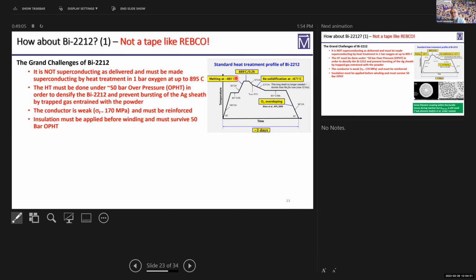And then we've lost oxygen up here, so we've got to let the oxygen keep going all the way down here. But the other issue is that because powder-in-tube has kind of 30% of void space, typically air, i.e. nitrogen and oxygen, oxygen can freely escape through silver, but nitrogen can't. So unless you provide an overpressure of, in this case, argon, so we have 49 bars of argon, 1 bar of oxygen, then it just bubbles and blows out and blows up the conductor. So this 50 bar is necessary.